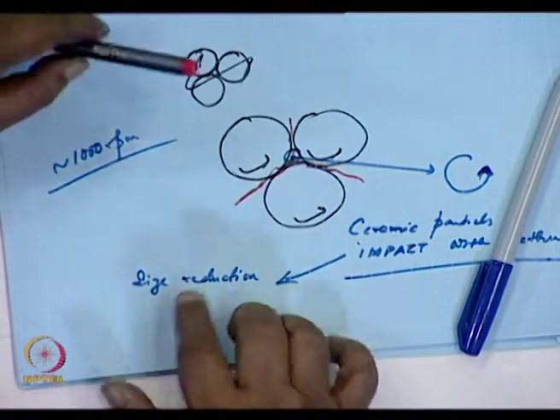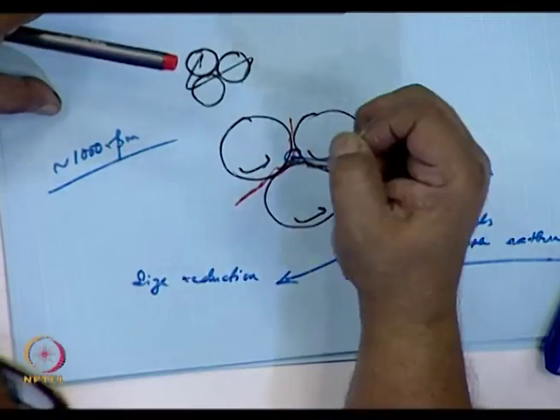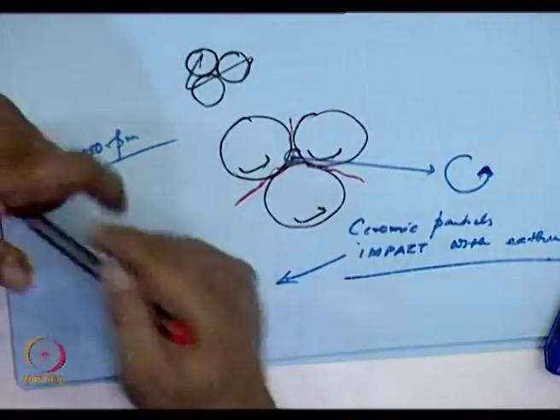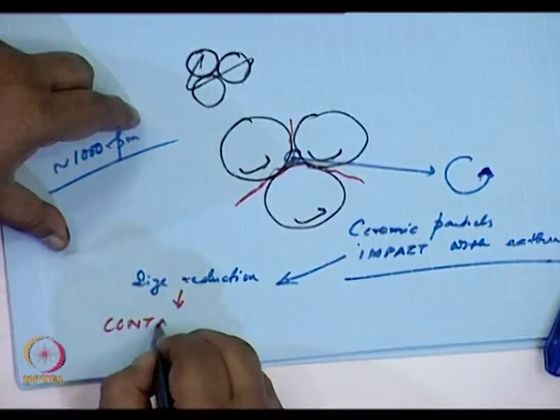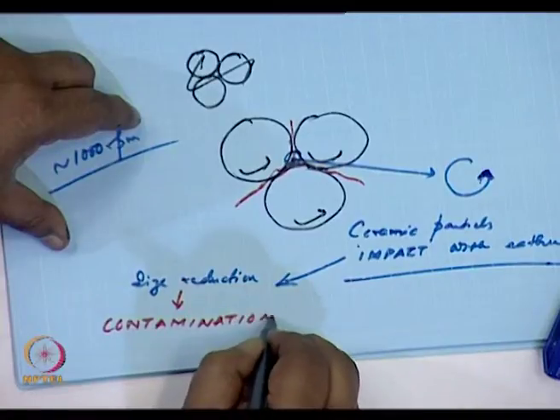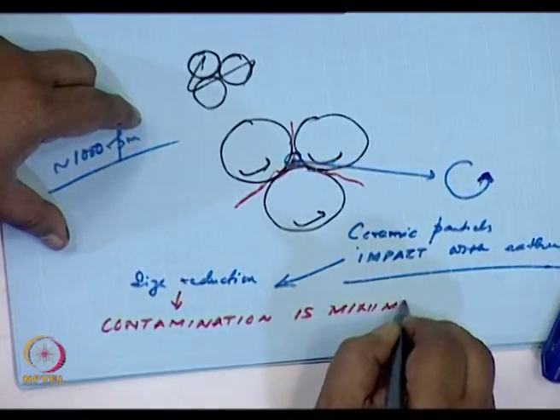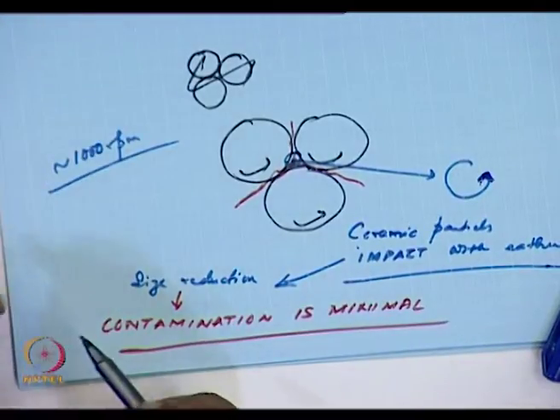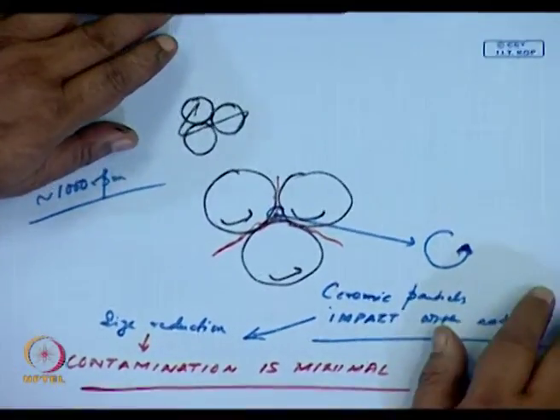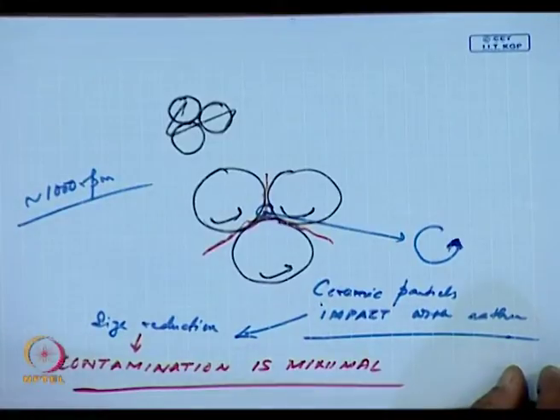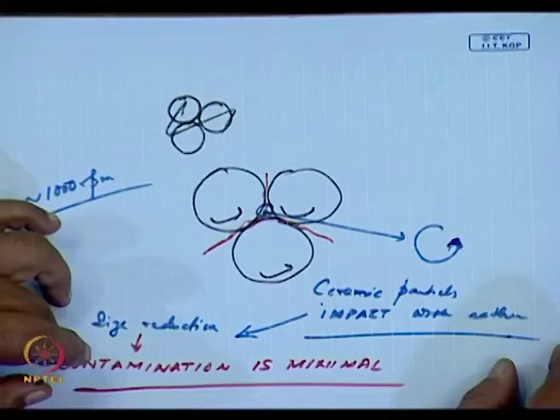Along with that, because here it is ceramic particle to ceramic particle impact, contamination is minimal. This is one of the major advantages of the planetary attrition ball mill. That is because here it is a particle-particle impact which is crushing the powder, rather than the ball impact in ball mills. Contamination is minimal. There is no scratching of the walls of the vessel by the balls. Hence, the wall contamination due to erosion of the wall is also minimal.